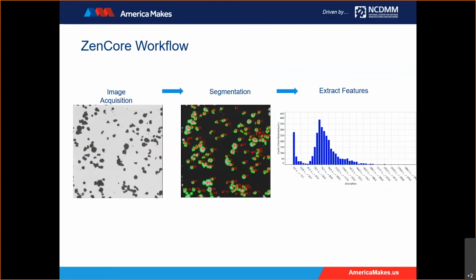Most often we're interested in the particle size distribution, so we can also plot a histogram of the max Feret diameter. In this plot on the right, you can see that we have a distribution with a peak around 60 microns. With just this analysis, you can tell a lot about your powder. You're probably most interested if you have a normal, bimodal, or multimodal distribution. In this case, in addition to the peak around 60 microns, we have a lot of fines, which we may be getting through during the sieving process and could have implications for the printing parameters that we should choose.